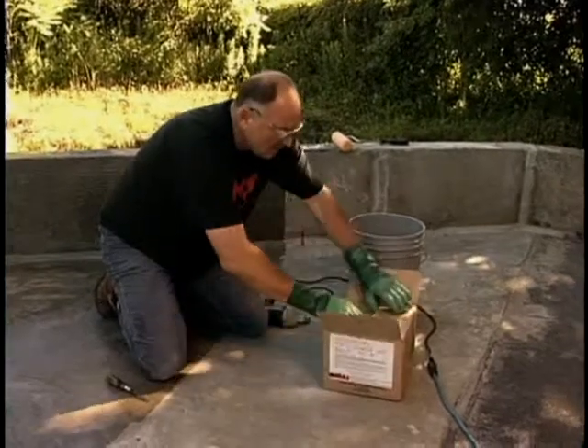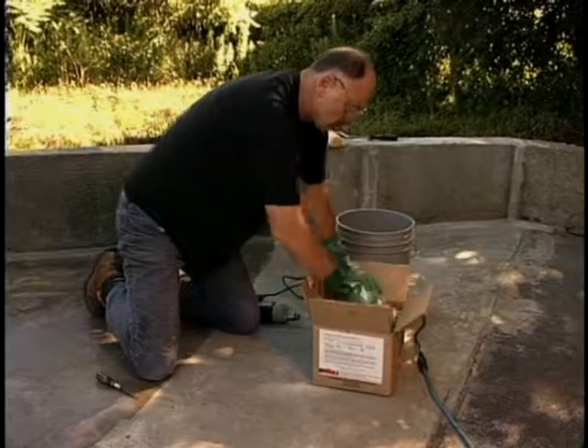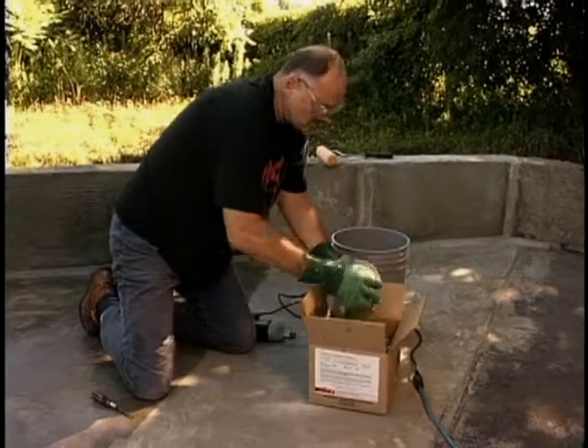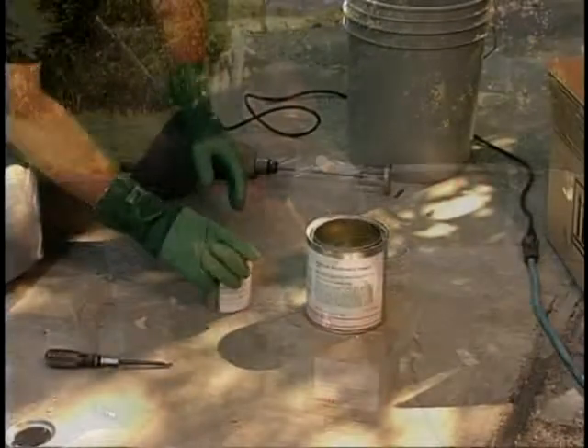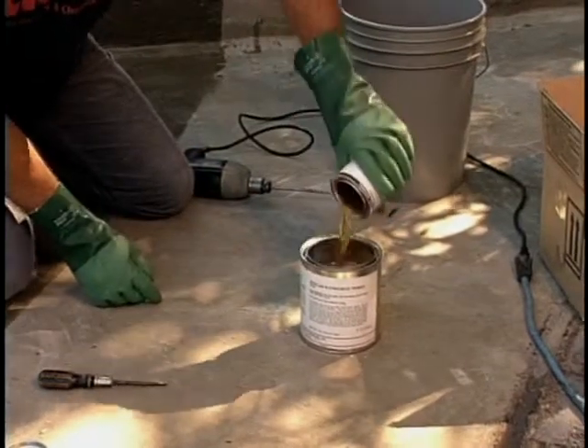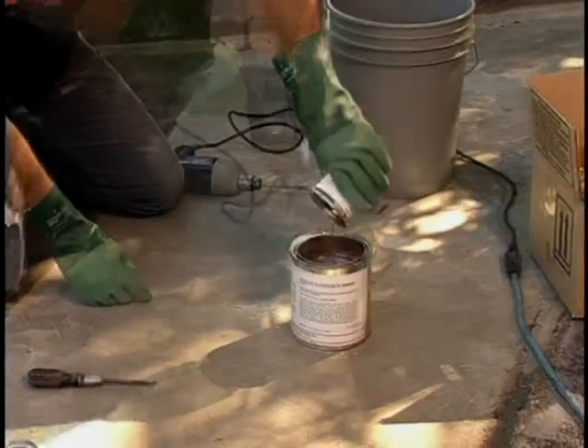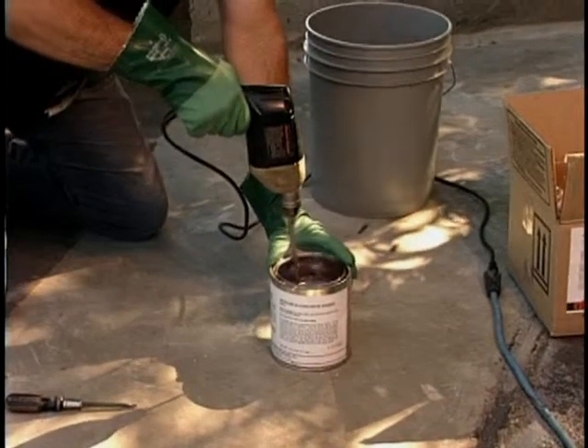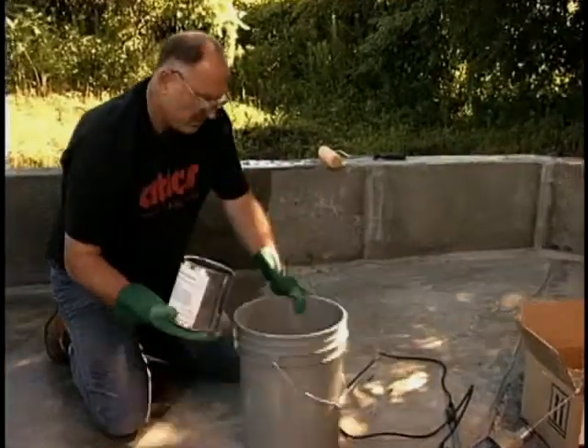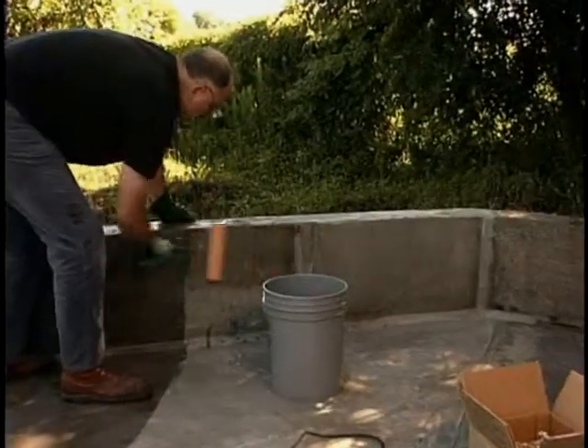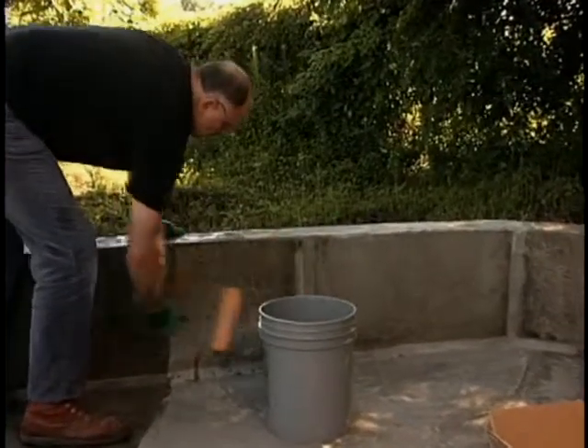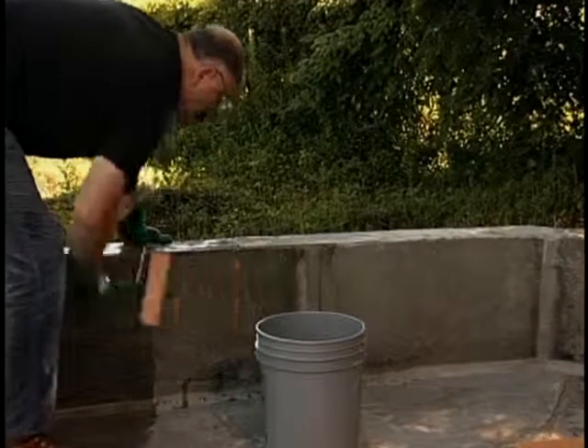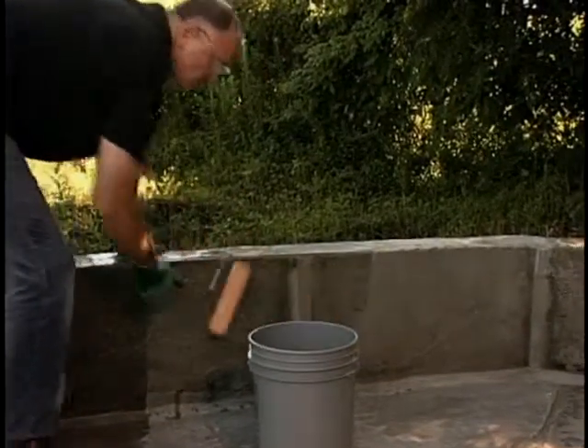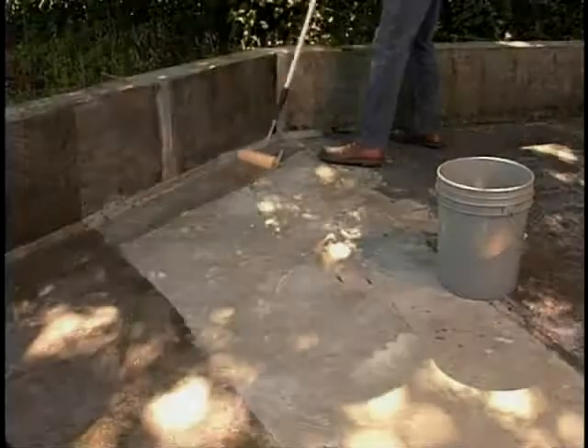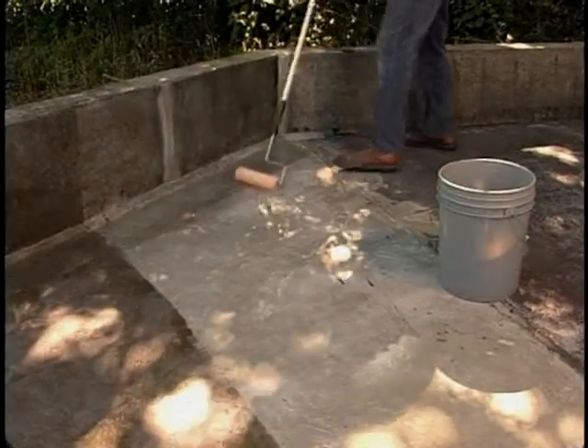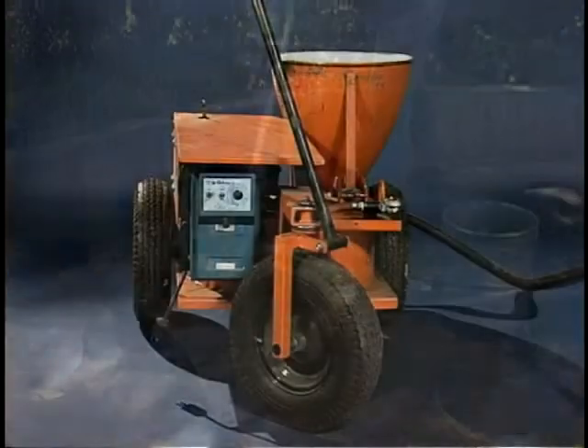After the surface is cleaned, it must be primed with Atlas Rezklad E concrete primer. Open both the resin and hardener cans. Pour the hardener into the resin container and mix with a mixing blade attached to a drill or by hand. Pour the mixed material into a pail. Apply the primer with a brush or a roller. Make sure that coverage is even and there is no puddling. The primed surface should be tacky or dry before applying the spray system. Repriming may be required after 24 to 48 hours depending upon the temperature.